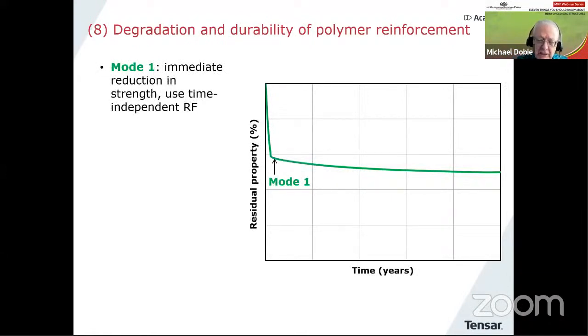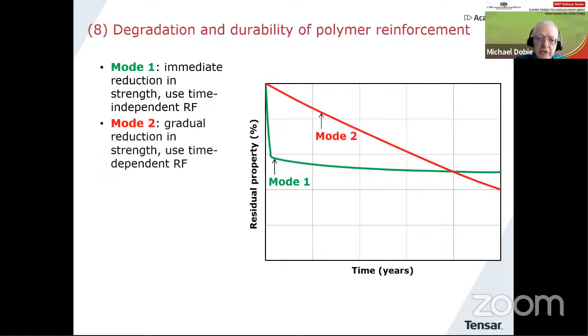Now, these are diagrams coming from that technical report I mentioned, where they designate forms of degradation procedures as in 3 modes. Mode 1 is where if we look at a residual property, which for example could be the tensile strength versus time, it drops very quickly at the beginning and then it doesn't change very much after that. Obviously, installation damage would be like that. And then mode 2 is a gradual reduction throughout the lifetime of the structure. That would be some chemical effects.